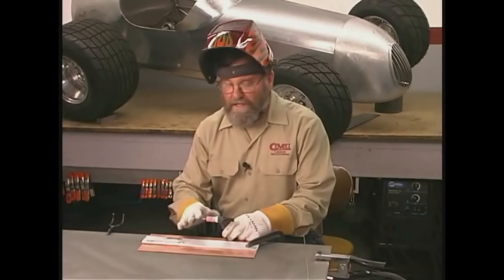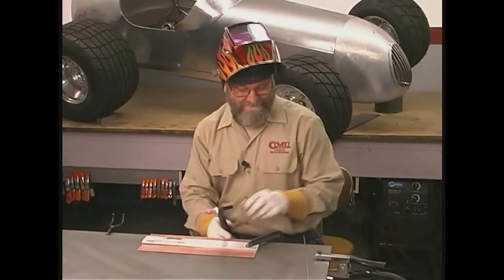For the next demonstration, I've intentionally stuck the tungsten electrode out way too far, and you'll see what effect this has on the weld. Even though I'm flowing a full 18 cubic feet per hour of argon, the weld area won't have a sufficient shield. I'll show you what I mean.